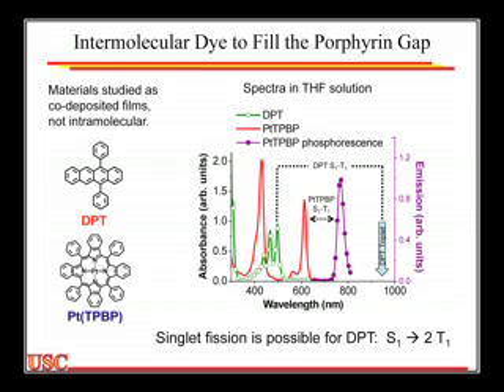Well, singlet fission is a process where I take one singlet excited state, I combine it with a singlet ground state, I show in this equation here. A singlet excited state and a singlet ground state makes 2 triplets. So in relaxing, remember when I thermalized before, each one of these little arrows is giving off multiple phonons, and so I'm just heating the crystal up. When I do this, I don't give off any heat at all. This is energy neutral. 2 triplets equals 1 singlet. I haven't given away any energy at all. There's no thermalization here at all.